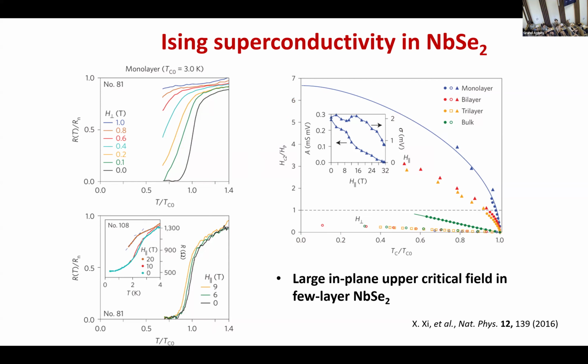This high field exceeding the Pauli limit is not specific. I think it's predicting. Exactly. For some other systems, you can also see a very large upper critical field exceeding the Pauli limit. So it's not necessarily the case. In our case here, we know the band structure quite well, and the band structure matches this interpretation of this observation.